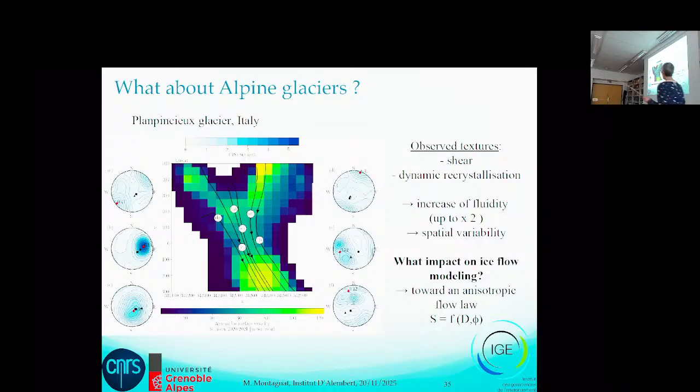Okay, so I've been working for a long time with VPSC, the viscoplastic self-consistent model. The good thing with this model is that we are able to put in the different slip systems. So we are considering basal, prismatic and pyramidal slip systems, but knowing that we have absolutely no proof from experiments of the existence of prismatic and pyramidal slip systems. So it's more a trick somehow: we know that we mostly have basal slip, and maybe we have something else, and we put it onto prismatic and pyramidal slip systems. So that's one way to model it.